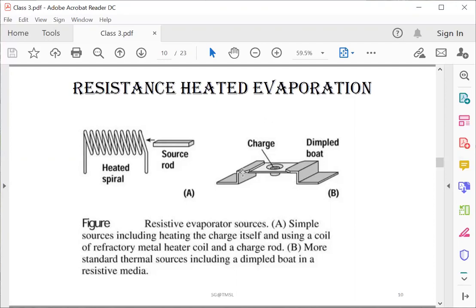There are two reasons. One, that particular portion of the filament will soften. And the second reason is again thermal expansion coefficient mismatch, if the temperature or heat throughout the filament is different at different points. Because of that there will be breaking of the filament, and that is why the life of the filament is too short.